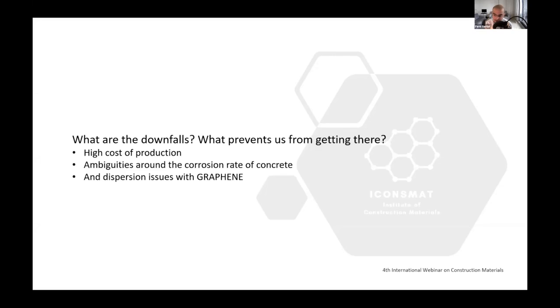Another problem with graphene when it comes to mixing in concrete returns to its hydrophobic characteristics. It just doesn't like to be mixed in water, which causes agglomeration, meaning that you will be seeing chunks of little black balls in concrete. And it's not good because you are expecting a continuous path for both electrical and thermal conductivity and not seeing chunks of black balls. But remember, we have so far talked about graphene and not graphene oxide.